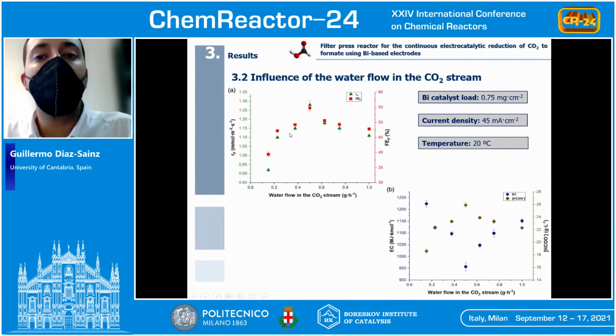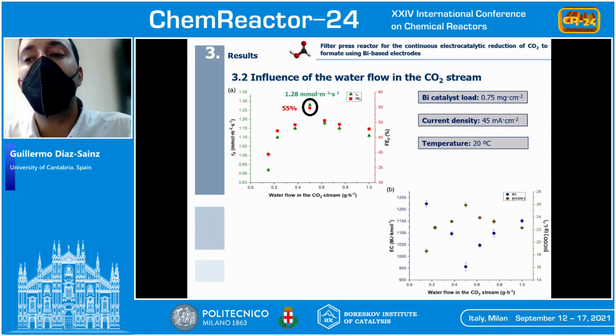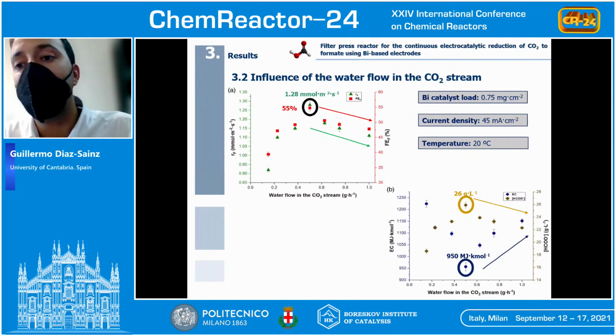About the influence of the water flow in the carbon dioxide stream, the same bismuth catalyst loading and the same current density values were used as in the influence of temperature. In this case, we can observe that working with a water flow in the carbon dioxide stream of 0.5 grams per hour, a formate rate of approximately 1.3 millimole per square meter per second and a Faraday efficiency for formate of 55% were obtained, and at the same time, at this same value, a formate concentration of 26 grams per liter with an energy consumption of only 950 megajoule per kilomole.